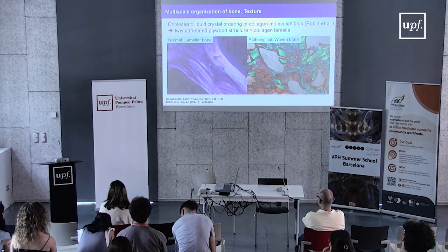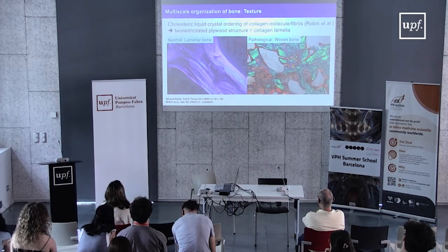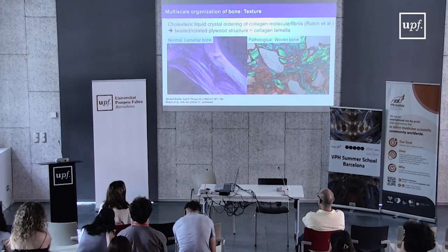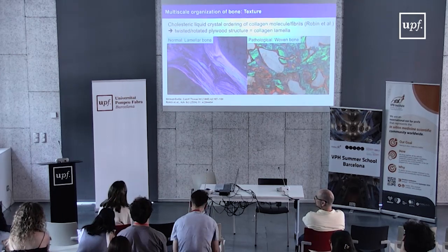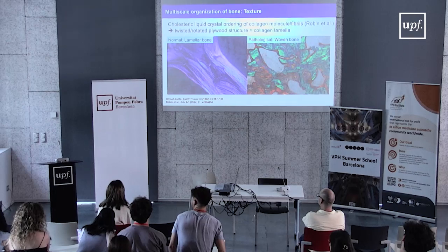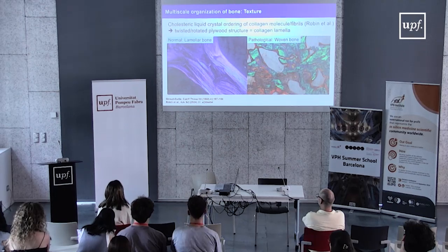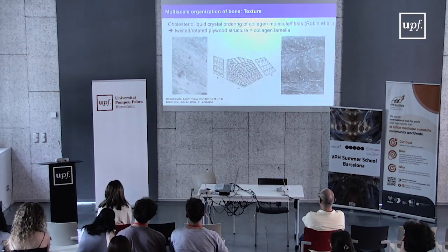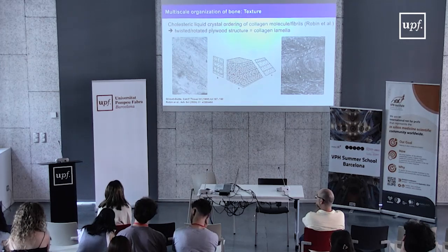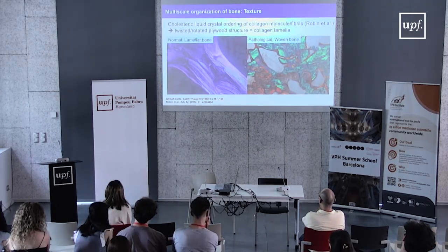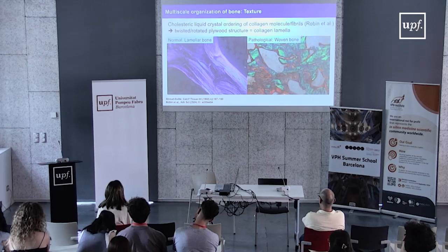When you have this pattern of organization, you will see by polarized light microscopy this type of structure, this polarization of the bone matrix with dark lanes that correspond to the fibers which are cut cross-sectionally, and bright lanes that correspond to the fibers that are cut longitudinally. This is a perfect resistance to fracture.